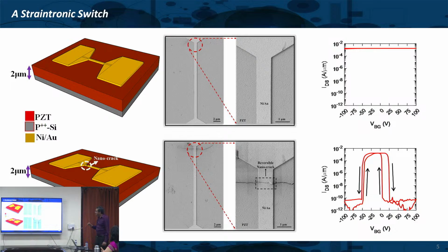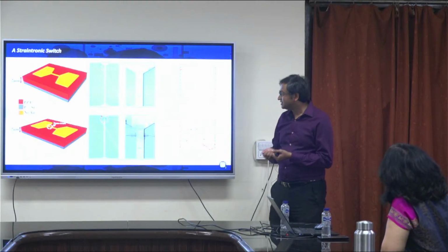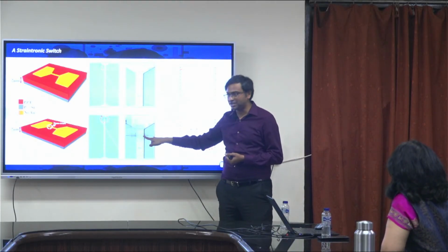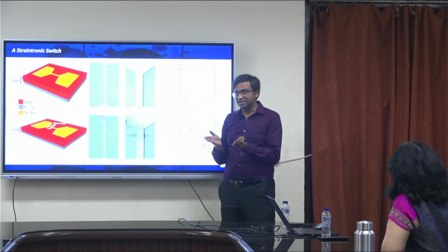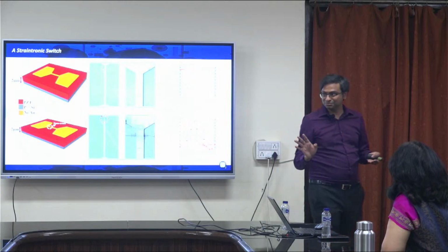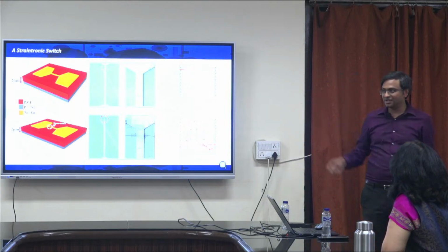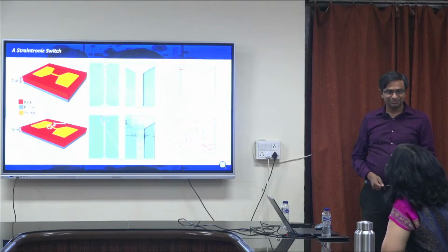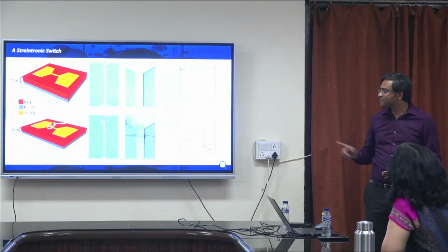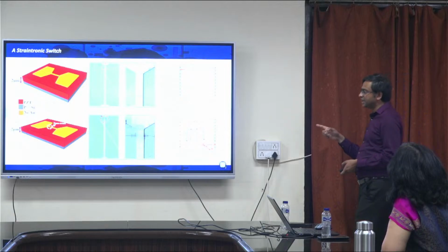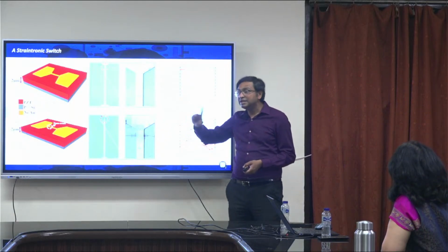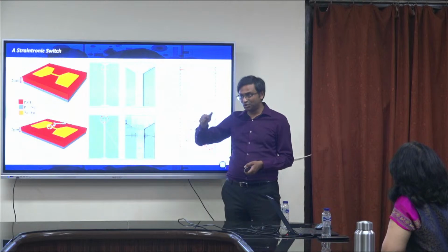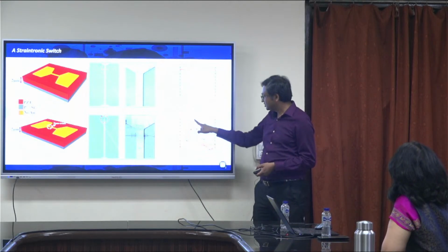Why? Because when you are applying a gate bias, you are also creating strain, and then the strain goes and creates a crack in my channel, which is reversible. Generally, cracks are never reversible, right? If you have a crack in a glass window, can you ever get it back? No, it just keeps increasing. But for the first time, we found that these cracks are electrically reversible. If you close the voltage, you see it comes back.